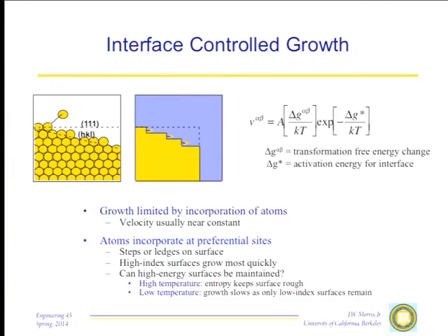And in fact, one of the great barriers as people developed theories of crystal growth and simultaneously theories of dislocations was how is it that crystals actually grow? Because if you get rid of the steps, then the only way you can continue growth is by nucleating new steps, by a two-dimensional nucleation process. And you can easily calculate that this is difficult to do. So back in the early 50s, when people were trying to get a good handle on how crystals grew out of the vapor, out of the liquid, they were having real trouble figuring out how you got past this nucleation barrier. Turns out there are two ways to get past it.